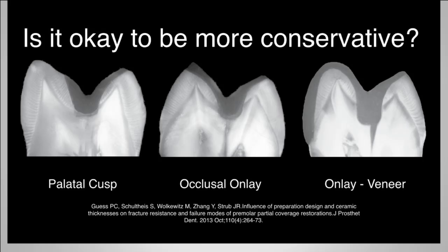What they found in each of these scenarios, they took all these restorations, they prepared them occlusally with occlusal thickness of 0.5, 1.5, and 2 millimeters. They then bonded these restorations in place, and they pressed on the teeth until they broke. And what they found was there was really no difference. Even with thin restorations, when we bonded them in place, they were able to take very, very high occlusal loads. Historically, I would have thought the thicker the restoration, the more tooth coverage there is, the stronger the overall restoration would be, the stronger the tooth would be. And we find that that's not the case.